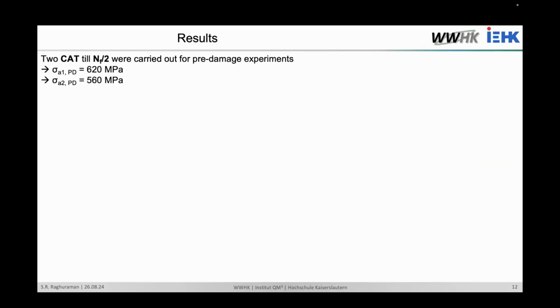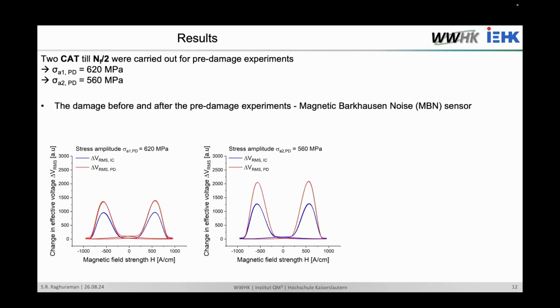So till now, we have talked about the procedure. Now we are going to talk about the pre-damage experiments. We have carried out pre-damage experiments at two stress amplitudes, one at 620 megapascals, another one at 560 megapascals. The damage before and after pre-damage experiments was also measured, in addition to other NDT with magnetic Barkhausen noise sensors. Here we see the so-called butterfly curves from the MBN sensor. We can see the change in effective voltage plotted against magnetic field strength. The red line is for the pre-damaged condition, and the blue curve is for the initial condition.